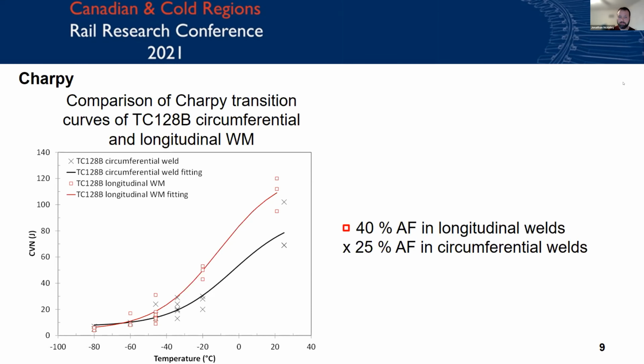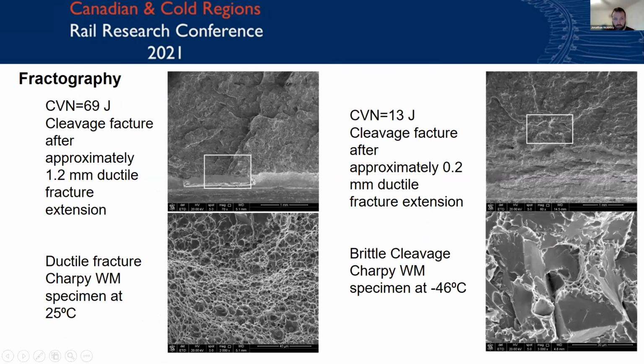And I've sort of mentioned two things in these curves. One is that the trend is not uncommon. It's a standard trend for temperature and welds, but we are seeing a substantially lower Charpy impact energy for the welds than the base material.